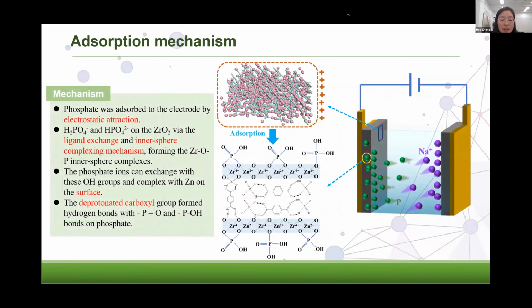These mechanisms mainly included that phosphate was adsorbed to the electrode by electrostatic attraction. The hydrogen phosphate ion and dihydrogen phosphate ion bind to zirconia via ligand exchange and inner sphere complexing mechanisms, forming zirconium-oxygen-phosphorus inner sphere complexes. The phosphate ions can exchange with the OH groups and complex with zinc on the surface. The deprotonated carboxyl group formed hydrogen bonds with the phosphorus-oxygen double bond and phosphorus-oxygen single bond.